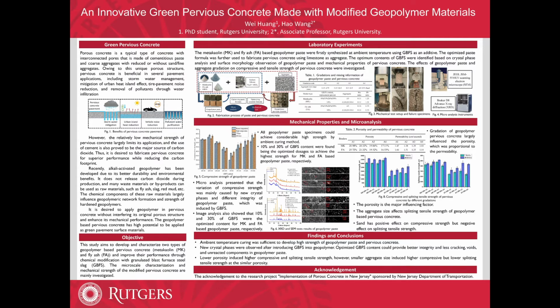However, when the porosity is the same or similar, if we compare the metakaolin-based pervious concrete with A1 to A3, as shown here, they have similar porosity, but their compressive strength reduces and their splitting tensile strength increases. So this phenomenon indicated that there is another factor affecting the variation of the strengths, which is the size of the aggregate. Going back to Table 1, we can find A1 has a smaller size, and A3 has a larger size. So we believe the aggregate size affects both compressive and splitting tensile strengths of geopolymer-based pervious concrete.